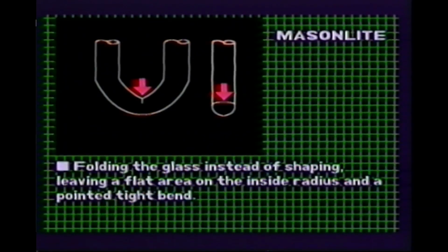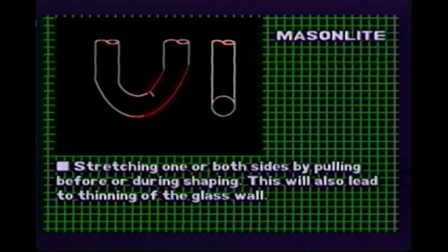The most repeated faults experienced forming this bend are folding the glass instead of shaping, leaving a flat area on the inside radius and a pointed tight bend. Stretching one or both sides by pulling before or during shaping. This will also lead to thinning of the glass wall.